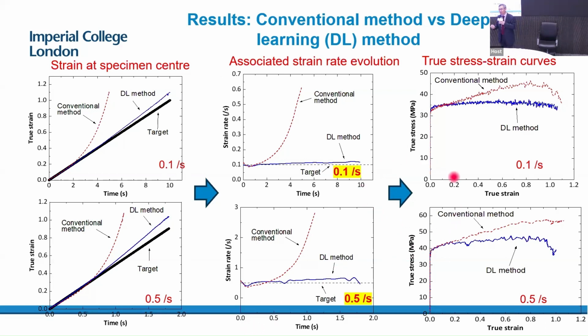And what we really want is the stress-strain data. For example, for the target strain rate 0.1, this is the true stress, and horizontal is the true strain. Previously, when we did the test, because the strain rate was not properly controlled, we got data like this. But with the proper control, we get data like this, which is significantly different from that one. For the strain rate 0.5, we observed similar features. And the flow stress error is over 25%.